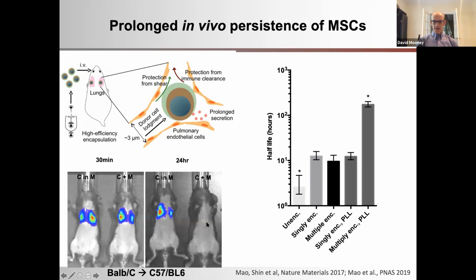The naked cells are basically gone 24 hours later, while the cells that we encapsulate, a high fraction of them are there. And if one looks at the half-life in the optimized system we've been recently developing, we now get about a 2-order magnitude enhancement of the durability of the cells. And so we think this is going to make a dramatic impact in terms of both allowing us to decrease the dose of cells that are needed, as well as significantly increasing their utility and their therapeutic effect.